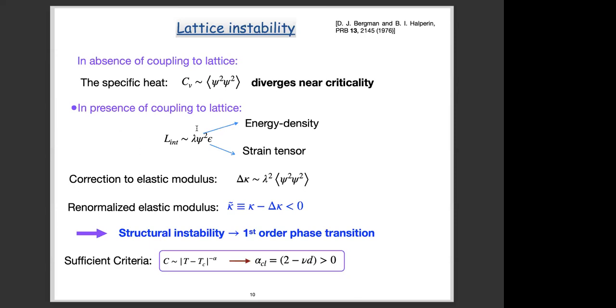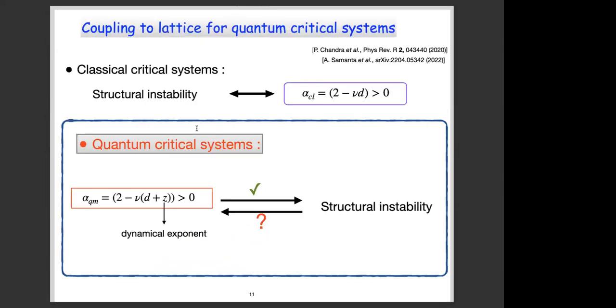Okay. So what we see is that, as we saw, the specific heat diverges near criticality, and near criticality it has a temperature dependence given by this equation, where alpha is the specific heat exponent. If alpha classical, which is related to the dimension and the correlation length exponent by this equation, becomes positive, this diverges. But now, in presence of such a coupling to the lattice, this classical critical system will, instead of a second order transition, exhibit a first order transition. In other words, the structural instability for such a coupled system implies that alpha classical is greater than 0, or vice versa. So if one has alpha classical greater than 0 for such a coupled system, one can expect the system will exhibit a structural instability instead of a continuous transition.